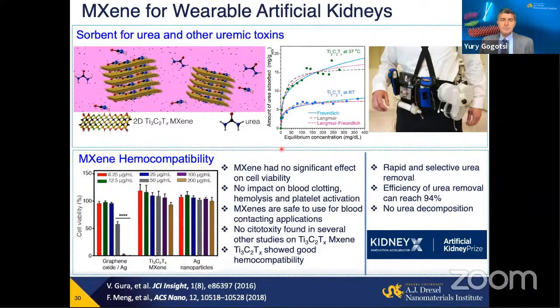And actually, the problem has become more acute because of the current pandemic. About 30% of patients who ended up in intensive care unit with COVID have significant kidney damage and require dialysis. In New York City, hospitals were running out of dialysis machines during the peak of the pandemic in spring 2020 here. So what prevents building a wearable kidney? There is no good sorbent for urea. Activated porous carbon, which is an excellent sorbent for the majority of applications, does not really adsorb efficiently very small urea molecules. MXenes appear to be a very good sorbent for urea.